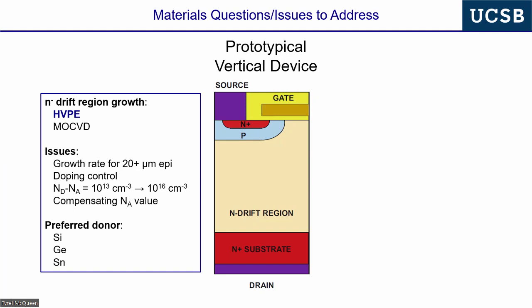If we do these substitutions onto the gallium site intentionally, then these species that are placed onto the gallium site have 1 extra electron compared to gallium. So they may donate those electrons to be free conduction electrons, okay? So that's the typical criterion for donors, that you look at adjacent columns in the periodic table to one of the host sites in the material, and hopefully you can then controllably put these impurities onto that site, okay, in very careful growth.